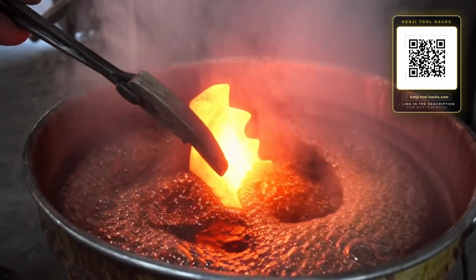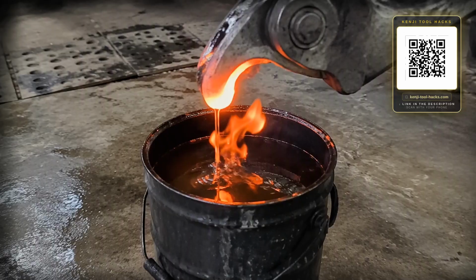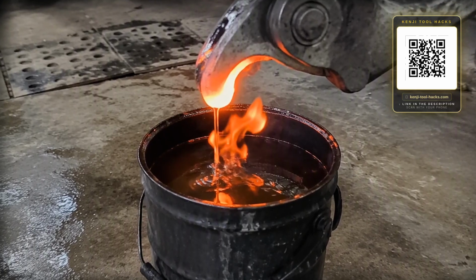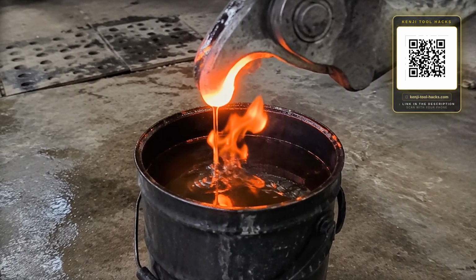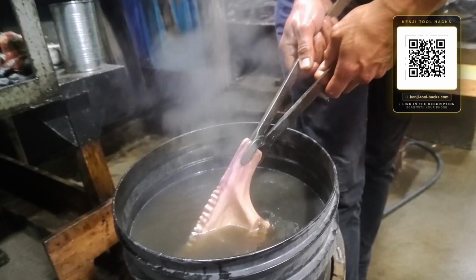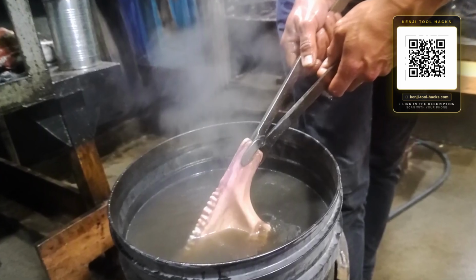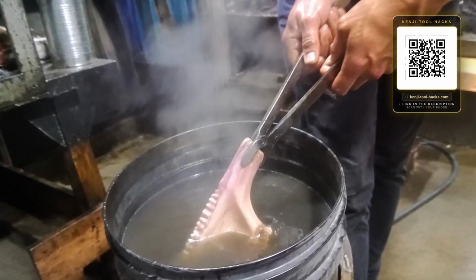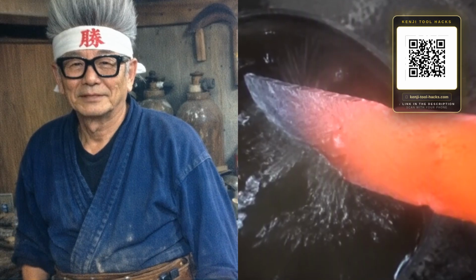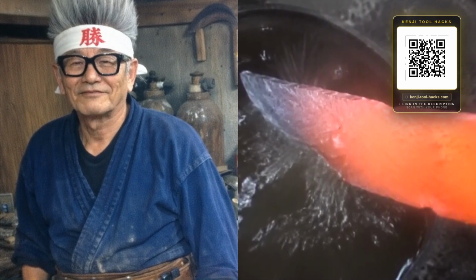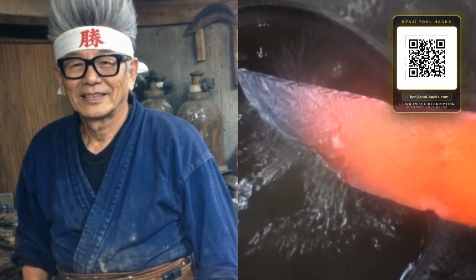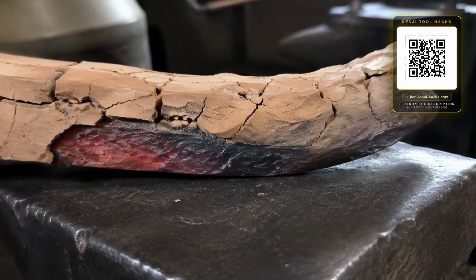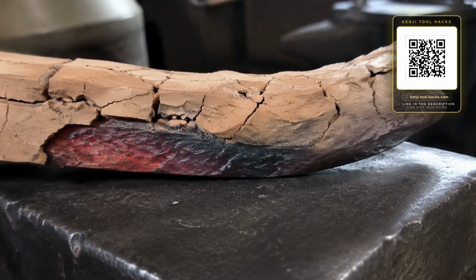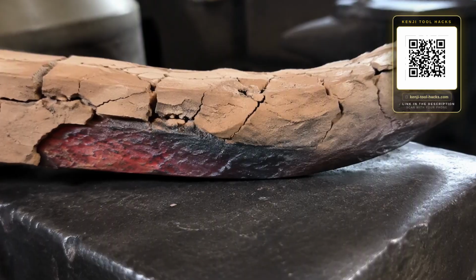That non-magnetic point is your green light, and it costs you nothing but a fridge magnet. The instant that edge is glowing and non-magnetic, quench it. Plunge the jaw edge first, straight down, into a bucket of warm water or, better for most steels, into oil. Edge first, and hold it steady. Do not swirl it wildly. The bare edge hits the liquid and freezes into hard martensite in a fraction of a second, while the clay-blanketed body cools slow and stays tough. You have just done tsuchioki on a bolt cutter.